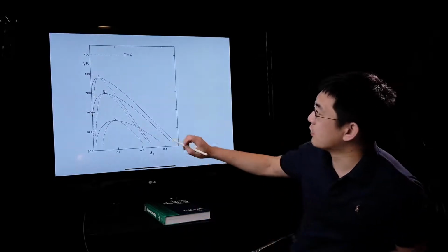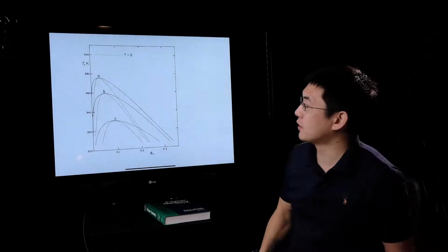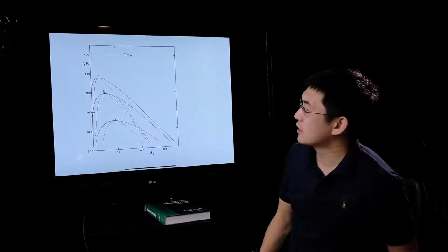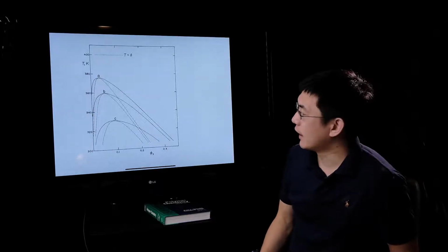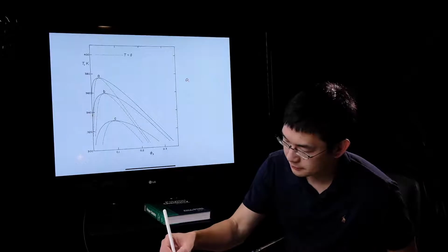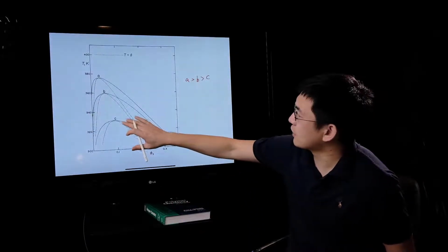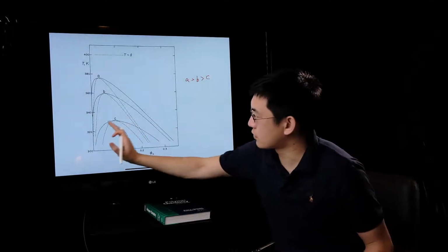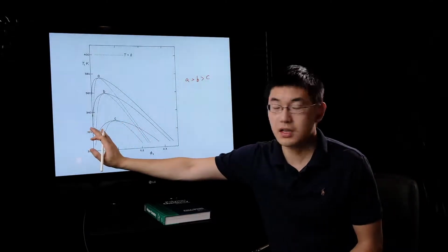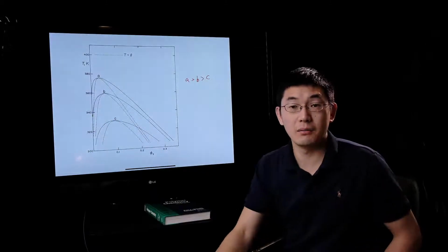If you increase the molecular weight, this is what happens in one of the reported results, where your critical data point is shown here. At higher molecular weight, your phase diagram is more skewed towards one direction, and this is due to the Flory-Huggins parameter.